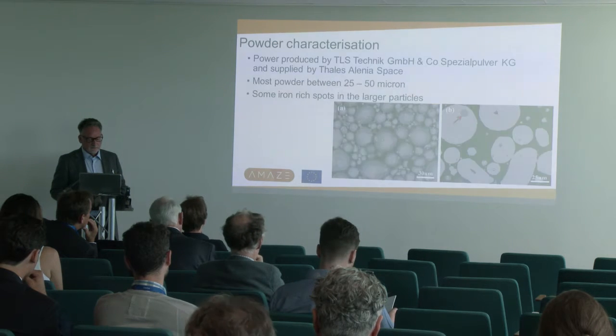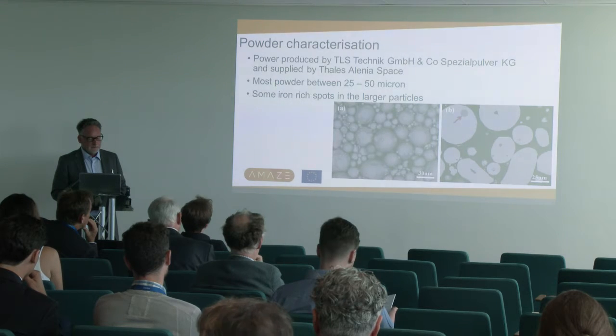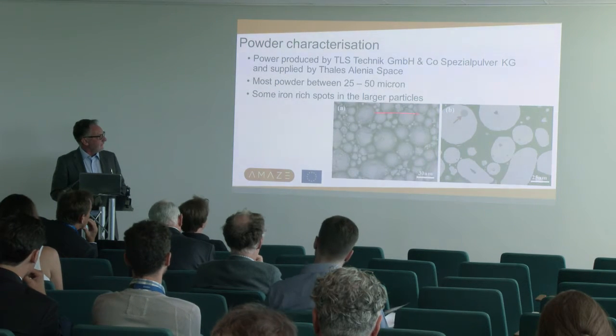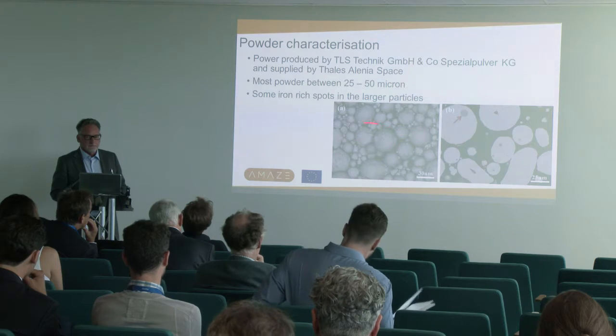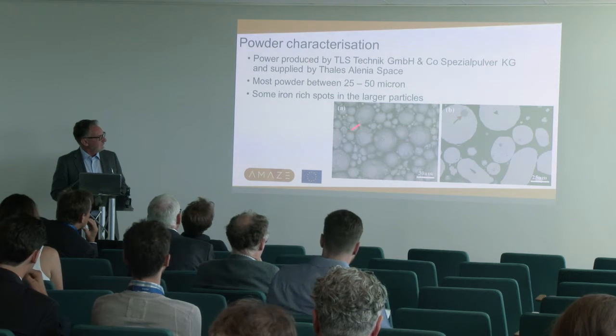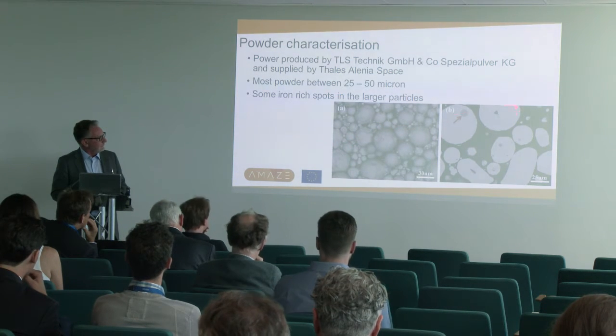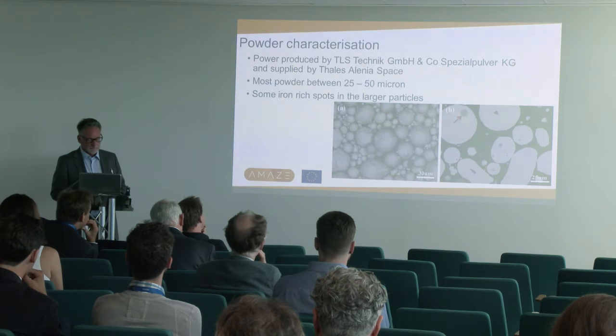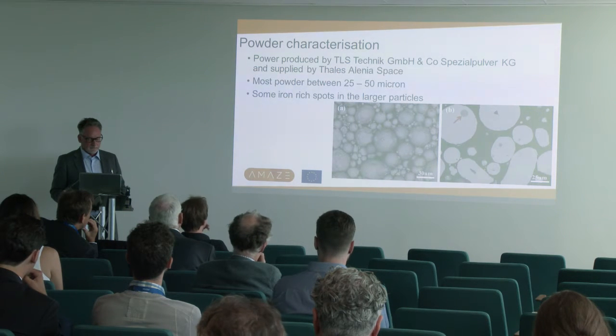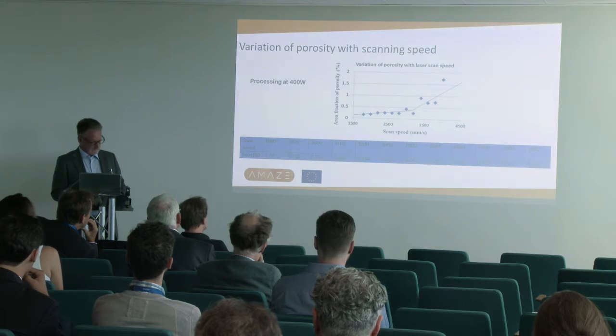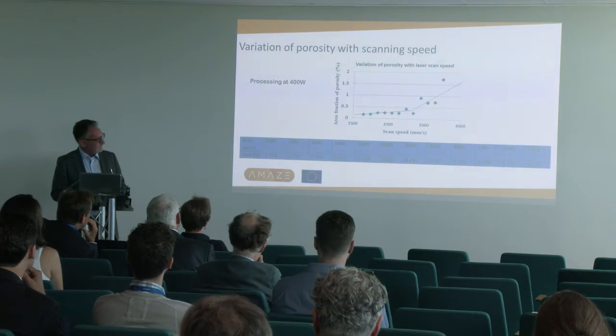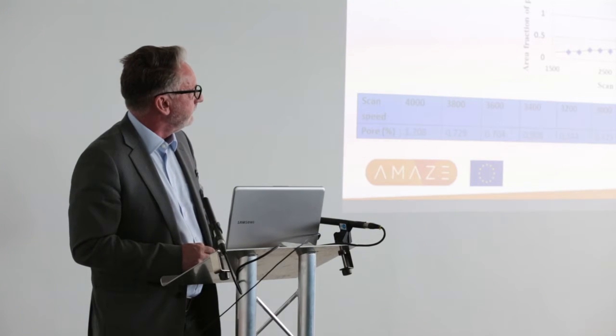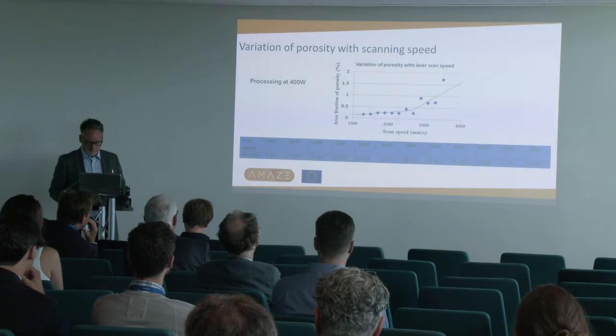We had the material produced by TLS again. The powder is quite nice, between 25 and 50 microns, and very spherical. There were a few iron-rich spots within the powder in some of the larger particles, but they didn't cause any problem. And again, we went through a case of optimizing the processing conditions. This is all processing at 400 watts, and then we're just doing some small trials at different scan speeds to see where we get the high-density parts.